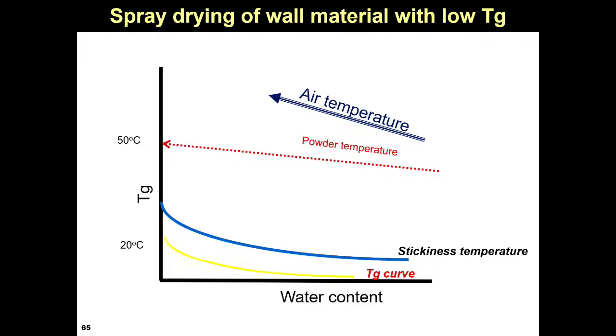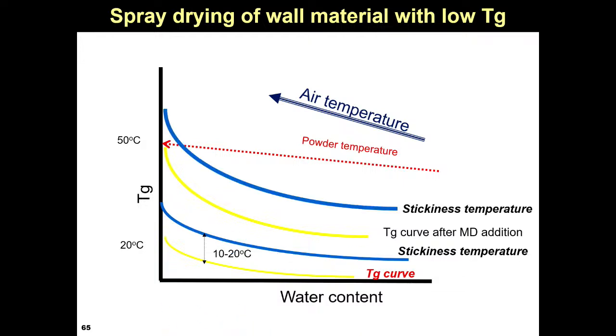The x-axis is water content, the y-axis is the glass transition temperature of the powder. So when we measure the Tg curve of the powder, higher than the glass transition temperature, this is the stickiness temperature. So in this very sticky raw material case, when we add some kind of maltodextrin, which has a high glass transition temperature, we can get a higher glass transition temperature of the raw material after maltodextrin addition. So the stickiness temperature curve is increased.